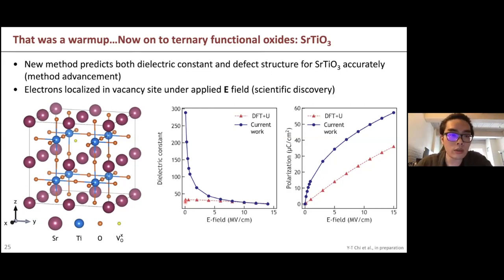So here we create a new method that can accurately capture the macroscopic material property, which is the polarization or the dielectric constant, and the nanoscale local electronic property, which is the electron behavior, at the same time. This is very important because it allows us to study the electron behavior in this kind of functional oxide, which has a relatively lower band gap than the alkaline binary oxide, under electric field.